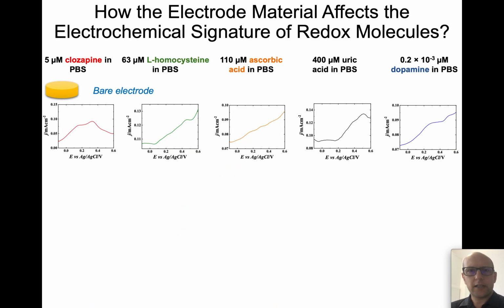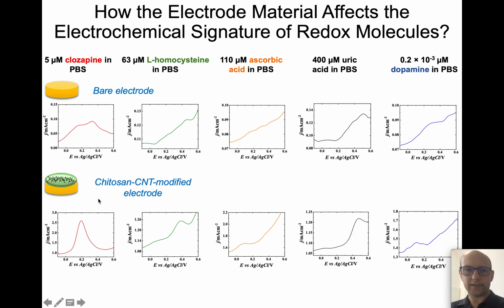So the first part, we wanted to ask ourselves, what is the contribution, or what is this electrochemical signature we measure from each one of the redox molecules, from clozapine and the main interfering molecules, and how the signal is affected by the modification with the chitosan-carbon nanotube. So what you can see here is the signature of the voltammograms from bare and chitosan-carbon nanotube electrodes, measured with clozapine by itself, L-homocysteine, ascorbic acid, uric acid, and dopamine by themselves in buffer solutions. And what we want to look at is, okay, we have the signature from a bare electrode and how the peak was shifted when we introduced the chitosan-carbon nanotube. It was done for each one of the interfering molecules, or each one of the redox molecules.